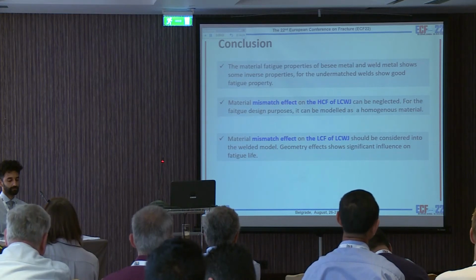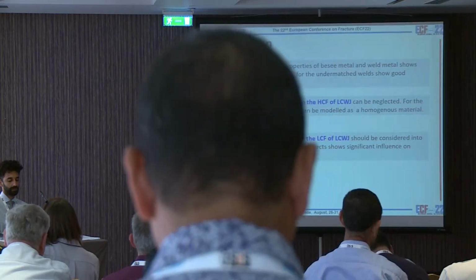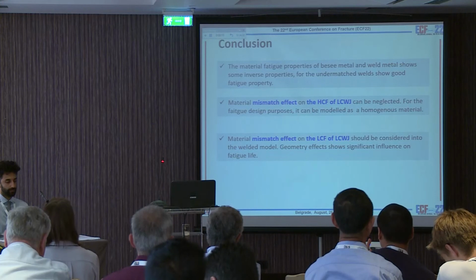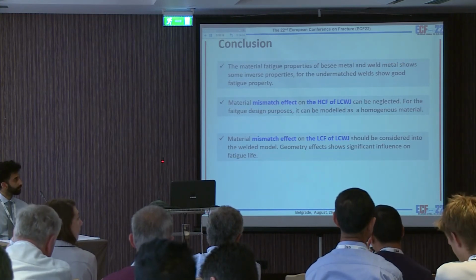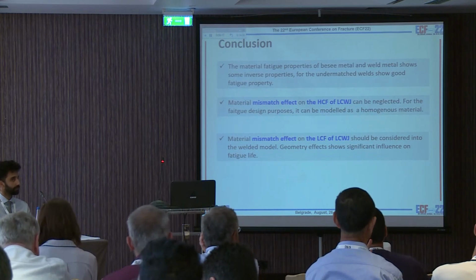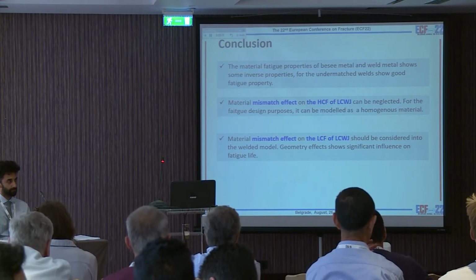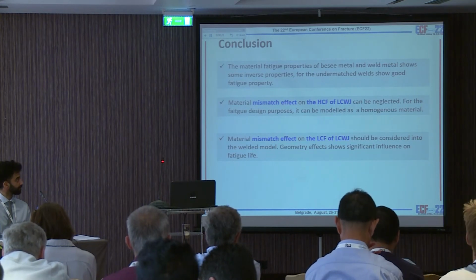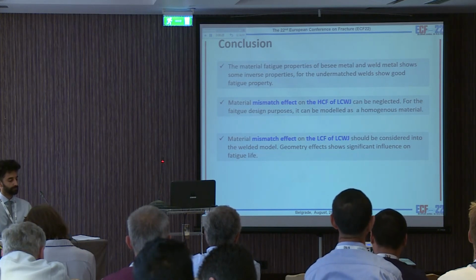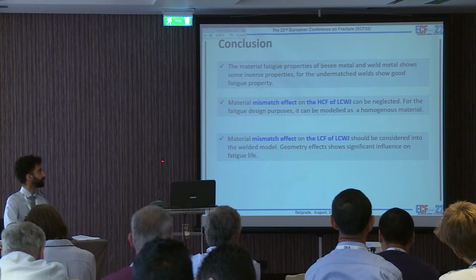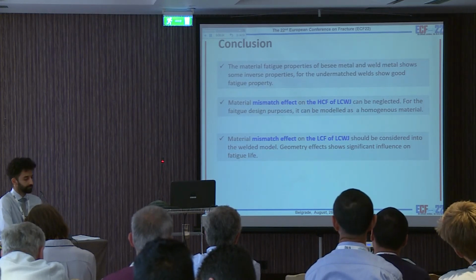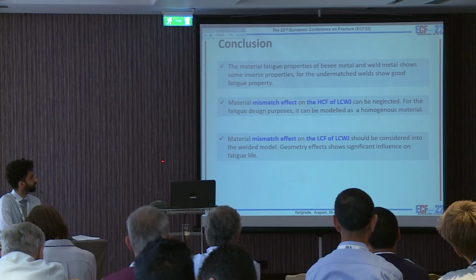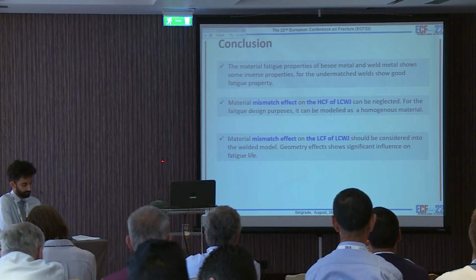So this is my conclusion. I should note that the material mismatch effect on the high cycle fatigue of the load carrying cruciform can be neglected. And for the fatigue design purpose, it can be modeled as a homogeneous model. And for the low cycle fatigue, the mismatch effect is not so large. It has some effect on the fatigue life, but I think geometry is the most important reason for the fatigue life prediction. So okay, thank you.